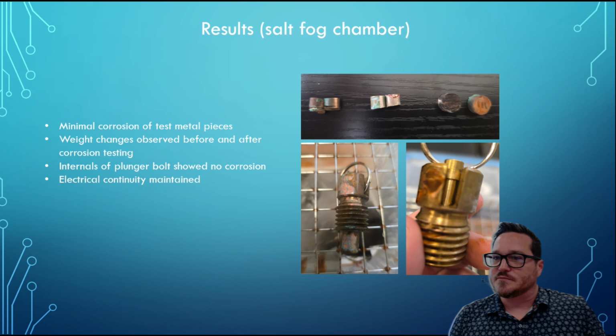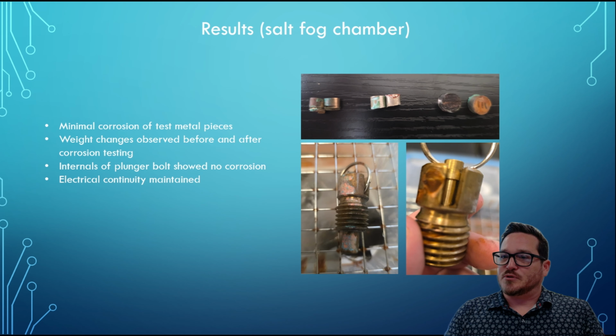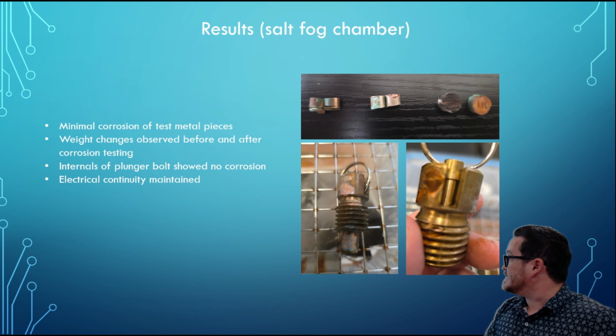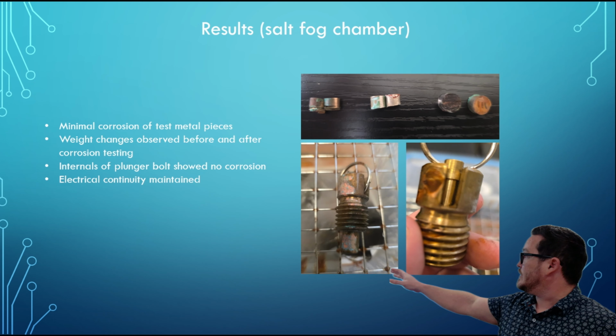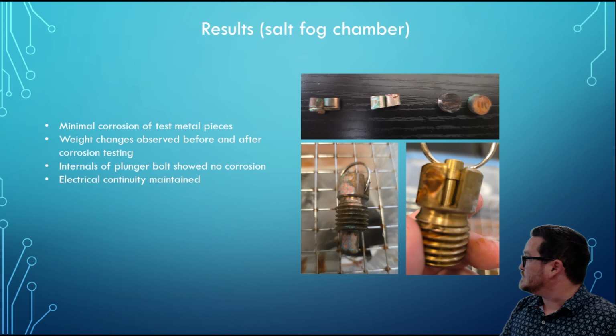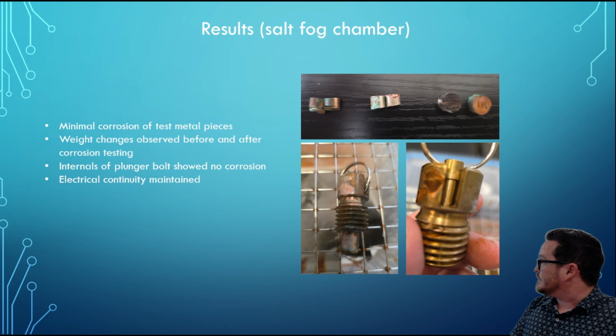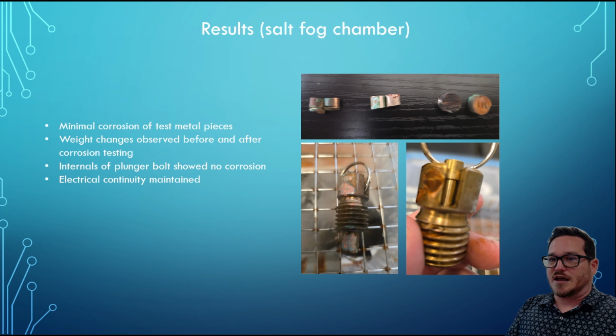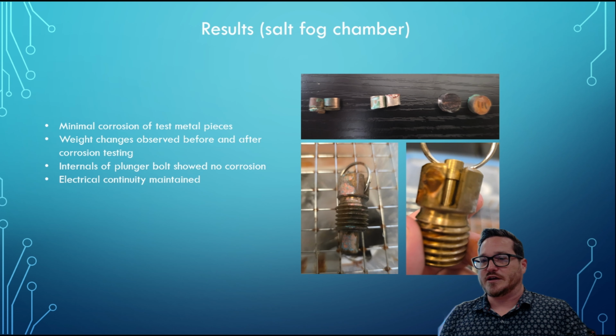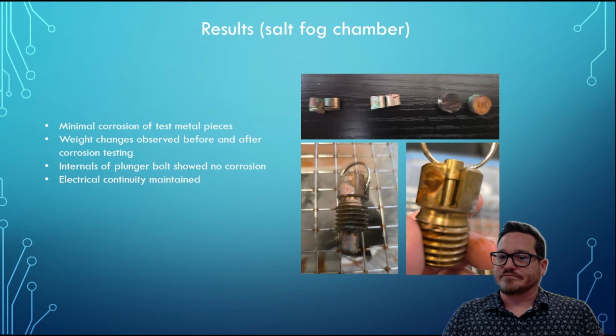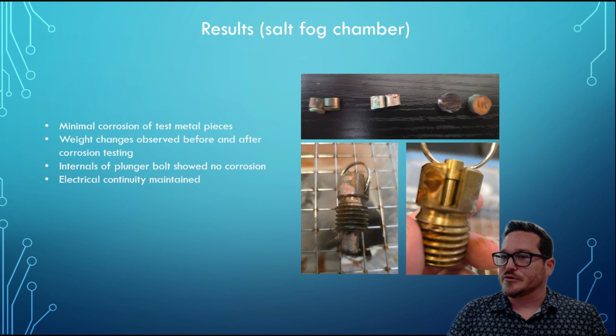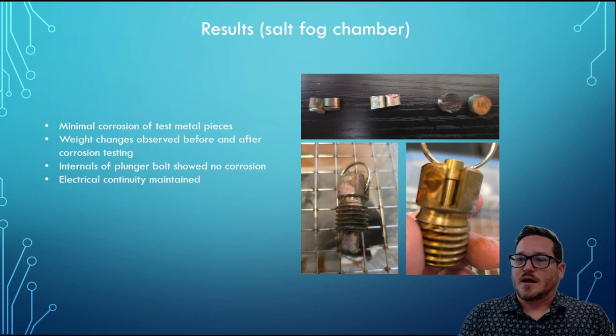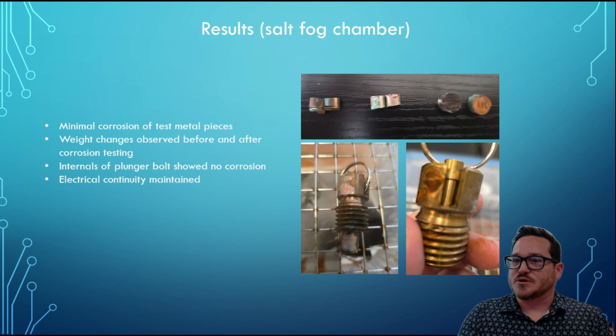These are the results from the salt fog chamber. The samples showed minimal signs of corrosion. On that top picture, you have the beryllium copper, and then the copper nickel, and then the phosphor bronze. There wasn't a lot of corrosion, however, the gold did tarnish a good bit, and I had to scrape some of it off just so I could get the electrical current to go through it. Changes in weight were observed for all samples.